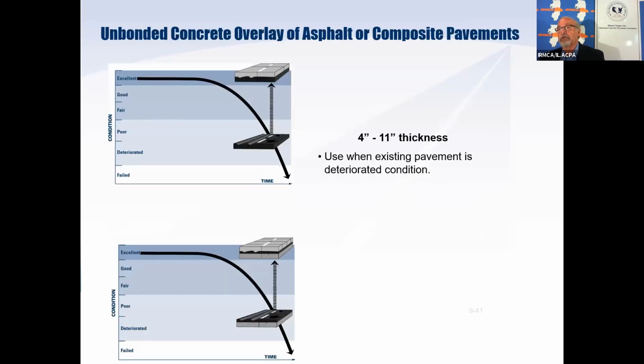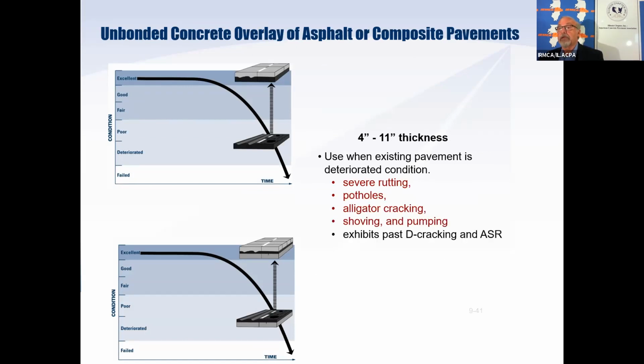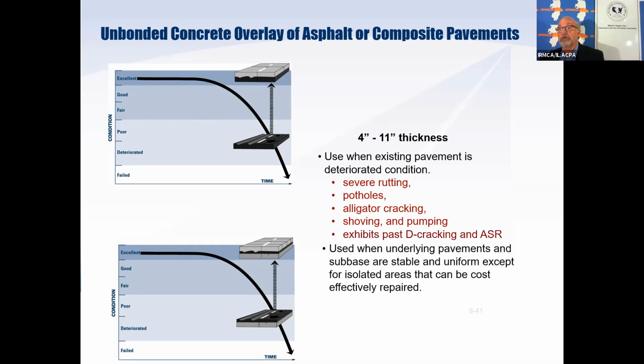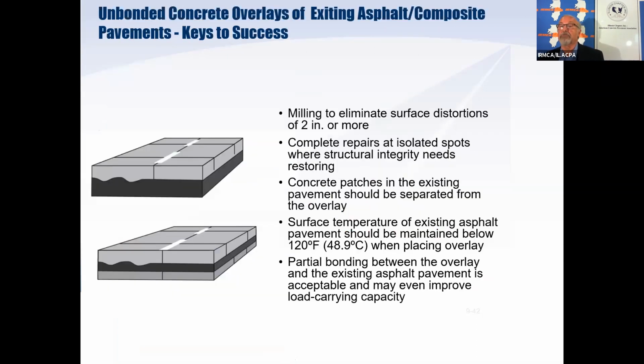We have unbonded concrete on asphalt or composite. Again, these are just constructing a new pavement on an existing pavement. The existing pavement doesn't have to be in even minimal condition to make this work, because you are assuming that the existing pavement is nothing more than a base course. So it is appropriate for severe rutting, potholes, alligator cracking, shoving and pumping, and ASR if it's a composite pavement. You can do this, and you should do this, when the existing pavement is not something you can bond to and add structural capacity to your overlay.